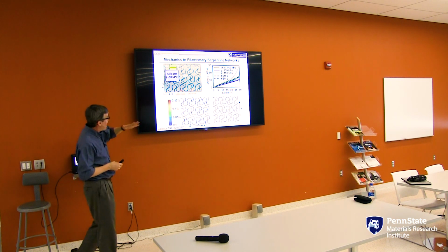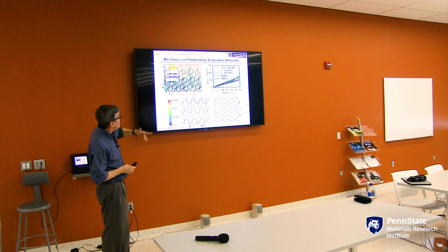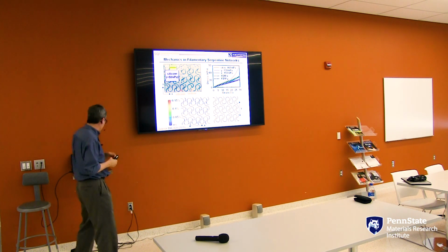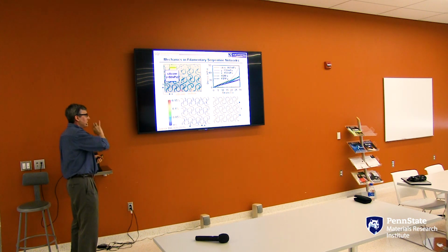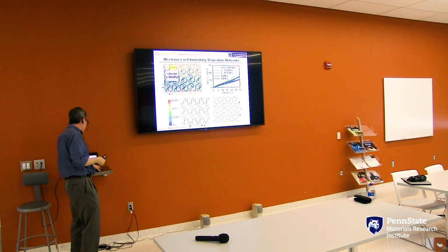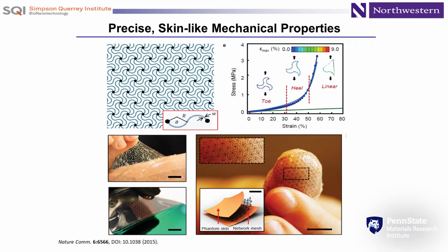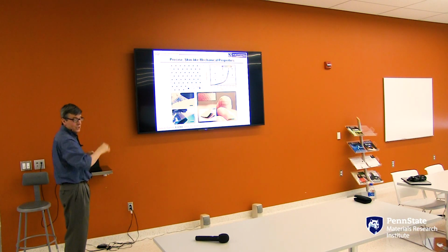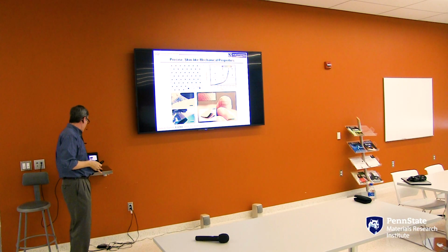So here we've matched the linear response regime of skin, illustrated in the red curve there. But all these biological systems, they have this J-shaped stress-strain curve. So you can actually go to the next level, and with more attention paid to the geometries here, you can achieve that same type of J-shaped stress-strain response in these artificial composite materials with tailorable tangential modulus across a range of strains that are relevant for biointegration.